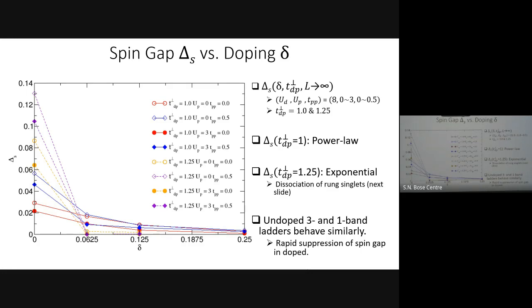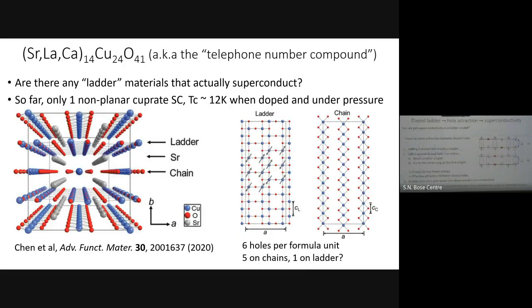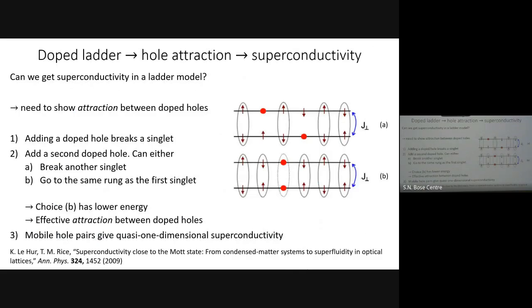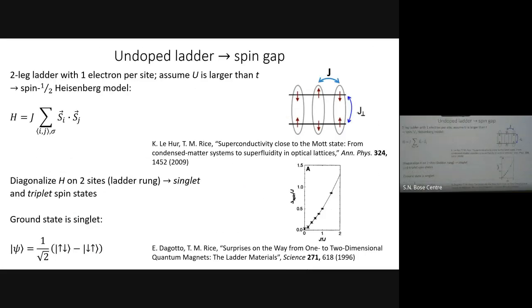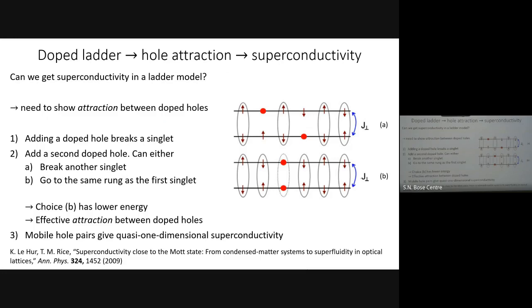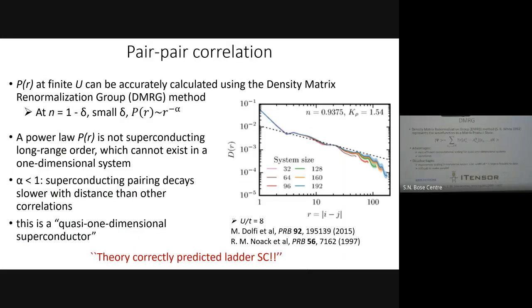Okay. So what we did was, remember, if I go back to this picture, the reason we have superconductivity is that if I have these here, then there are singlets here. So the system still has a spin gap. It is because it has a spin gap that they move like this. So the spin gap and superconductivity are related. This is also true within the BCS theory. You can't have one without the other. So one of the things people calculate is the spin gap, which we did for our three-band model.